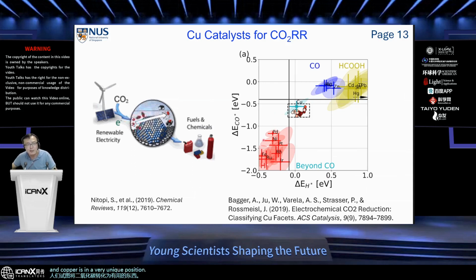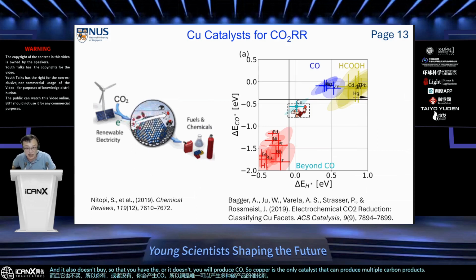It doesn't bind the CO too strongly, and it also doesn't bind so weakly that you will only produce CO, right? So copper is the only catalyst that can produce multiple carbon products like C2, C3 products in significant amount. So that really attracts a lot of research attention. If you read CO2RR papers these days, it's always copper.